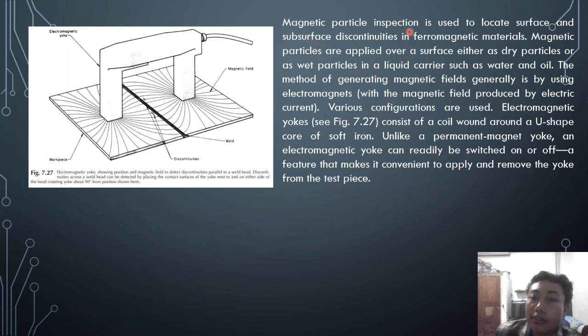Magnetic particle inspection detects local surface and near-surface discontinuities in ferromagnetic material. Magnetic particles are applied over the surface either as dry particles or as wet particles in a liquid carrier such as water or oil. The metal is magnetized, generally by using electromagnetic methods, with the magnetic field produced by electric current. Various equipment is used, such as the electromagnetic yoke seen in Fig. 7.27, which consists of a coil wound around a U-shaped soft iron core. Unlike the permanent magnet yoke, the electromagnet yoke can be readily switched on and off, and the magnetic field applied and removed from the test piece.